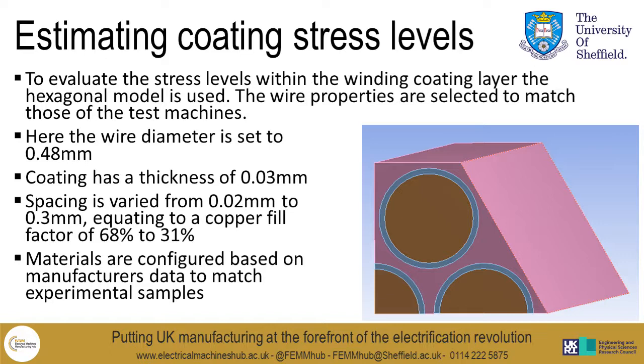Again, the spacing was varied between 0.02 millimeters and 0.3 millimeters, which can be equated to a copper fill factor of about 68% down to 31%. Materials which are used in this model are configured based on the manufacturer's data to try and match it as closely as possible.